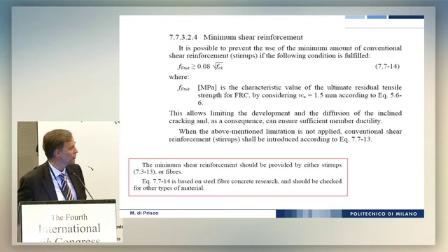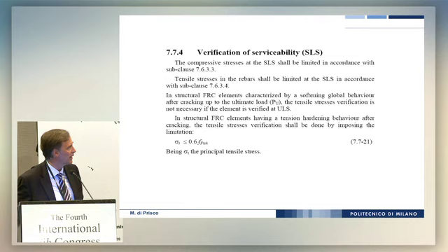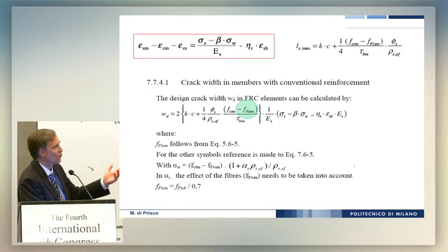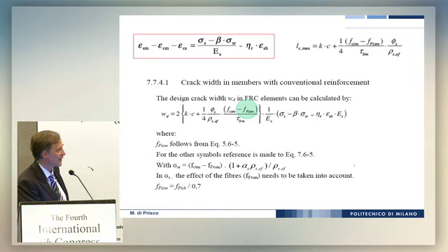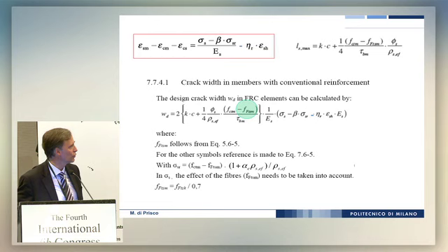About serviceability, there are some statements related to the high strength hardening material, which is not so important, because it's not so easy to find hardening material in practice. But about the softening material, you see that there is a strong contribution in the crack width computation, so you have essentially this term which reduces the crack opening.